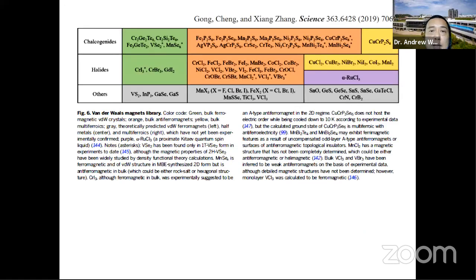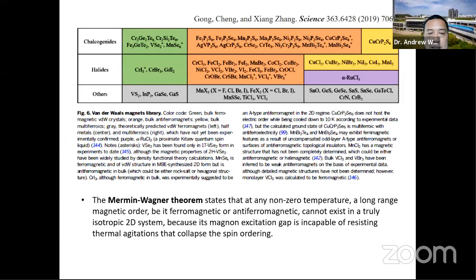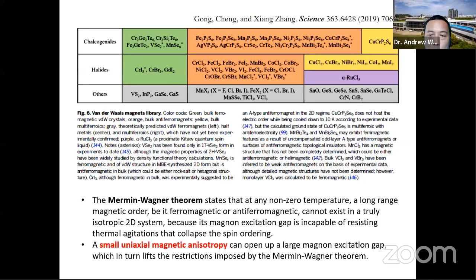This is a review written last year by Xiang Zhang's group, summarizing the 2D van der Waals magnets found so far. And as said just now, the Mermin-Wagner theorem says that normally you can't get long range order because of thermal fluctuations. But if you include some anisotropy, you can open up what is known as a magnon excitation gap, and you will lift restrictions imposed by this Mermin-Wagner theorem.